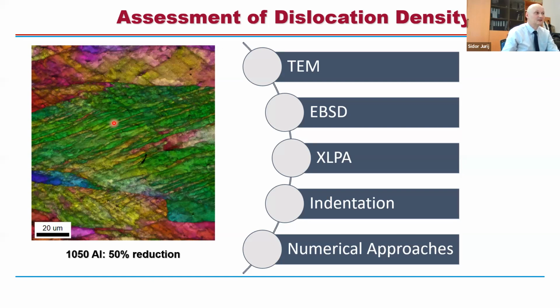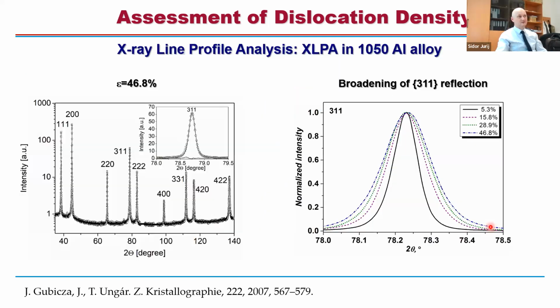We observe deformation bands, deformation cells. So normally the evolution of dislocations is investigated by transmission electron microscopy, electron backscattering diffraction, X-ray line profile analysis, indentation techniques, or numerical approaches. TEM is also quite time-consuming, and the equipment is quite complex, right? So very often people try to avoid using transmission electron microscopy if it's possible. So in my talk, I will concentrate on EBSD, X-ray line profile analysis, indentation, and other numerical approaches.